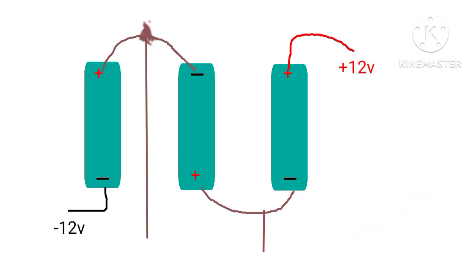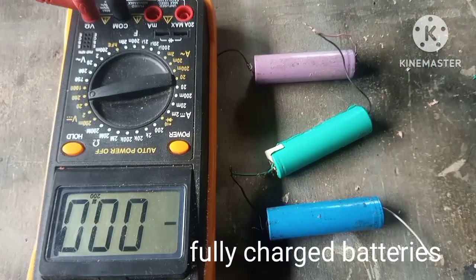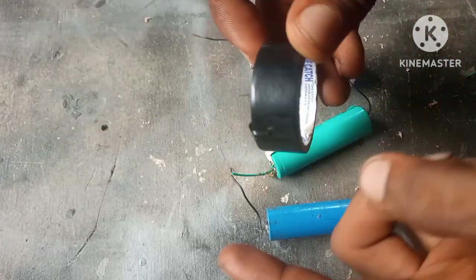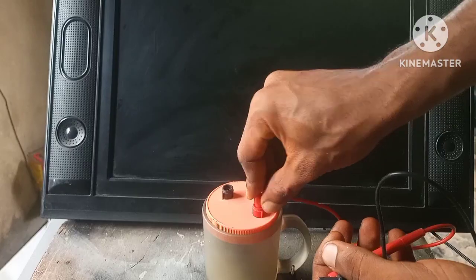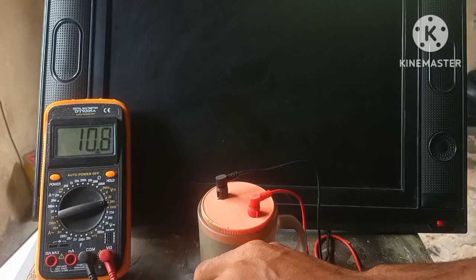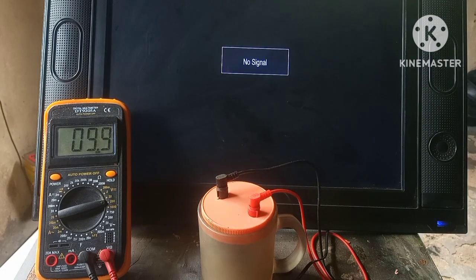Now let's talk about discharging the battery. The minimum discharge voltage for a lithium-ion cell is 3.1 volts — discharging below that will damage the cell. With three cells at 3.1 volts the total minimum voltage is 9.3 volts. To avoid damaging the battery, hook up a multimeter at the two ends and monitor it. It's a lot of work monitoring the battery while watching TV, but this process will protect the battery from damage. To make the project fun, I used a mug as a battery case.